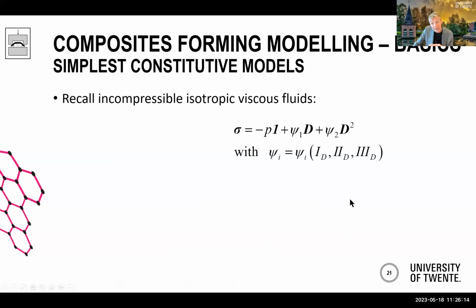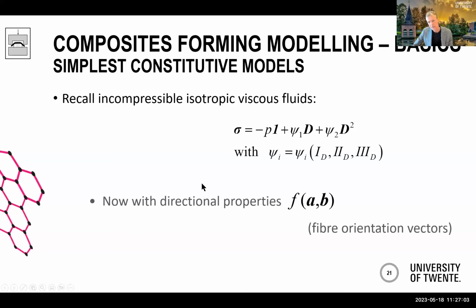Now we need to go from strain to stresses. Okay, and yeah, we're using a viscous-like material, right? Apart from the fibers, then. So how was that for viscous materials? Well, this is the classical, most general viscous law, where the Cauchy stress tensor contains a hydrostatic part and can be written as a function of the rate of deformation and the square of the rate of deformation, where these factors psi are a function of the invariants of the deformation rate. And in this case, we want to go to fluids with directional properties.